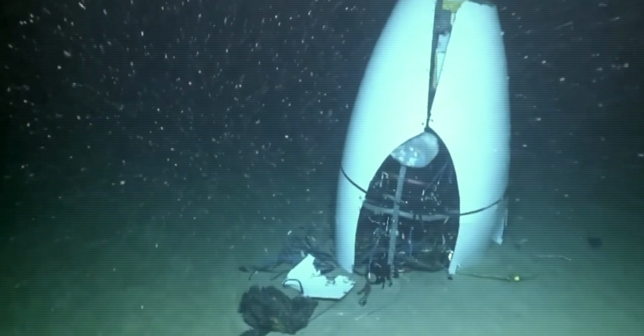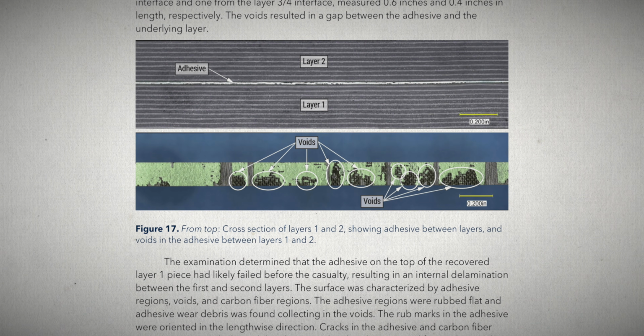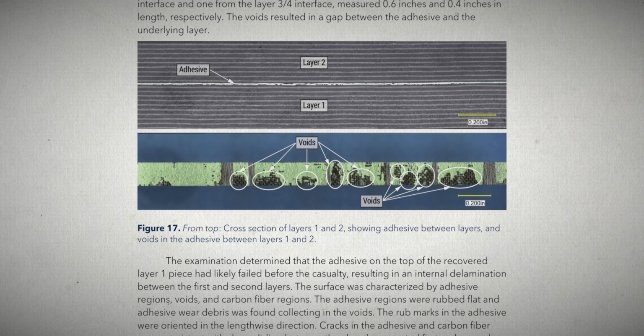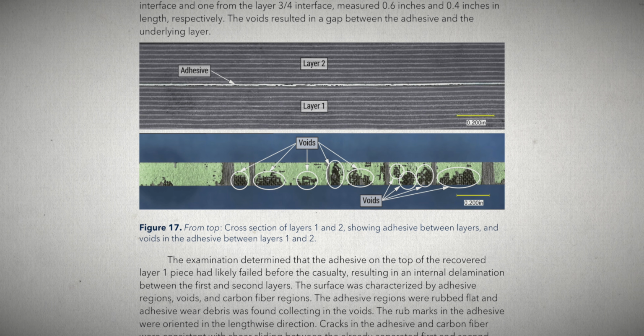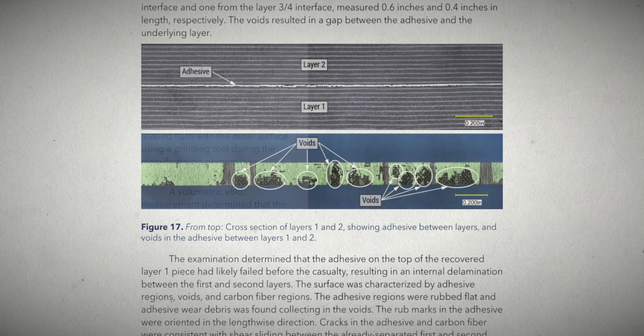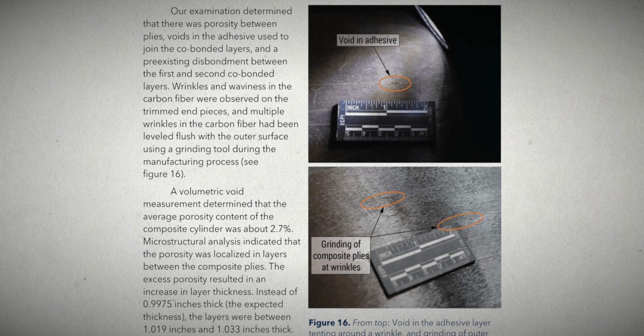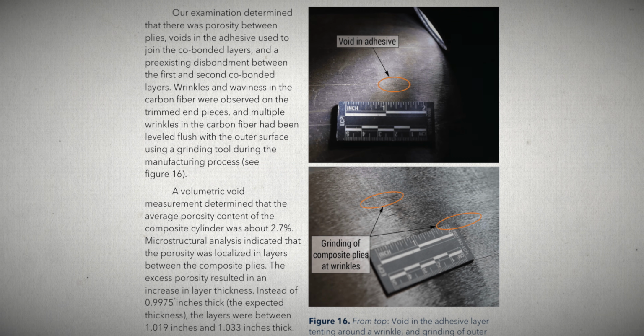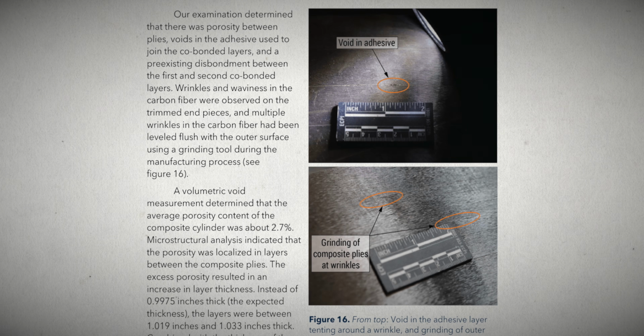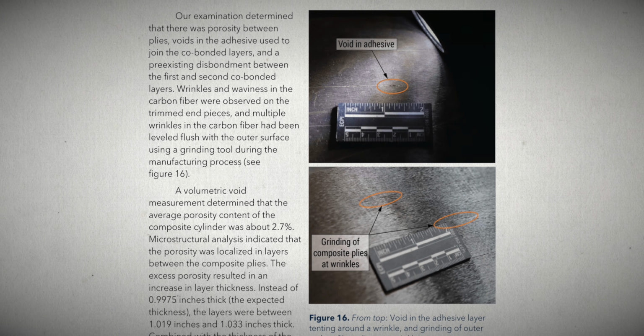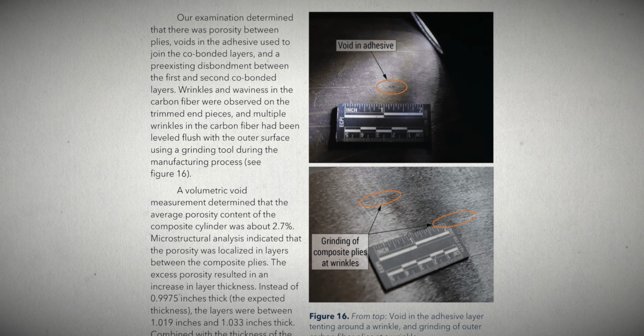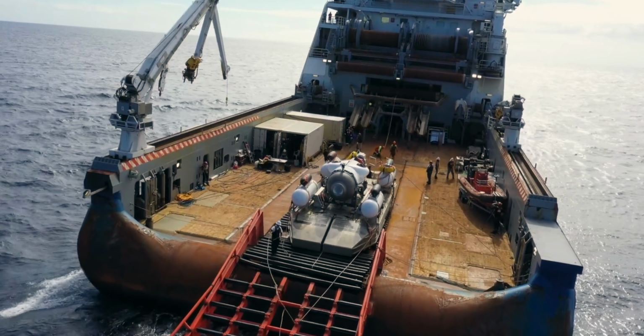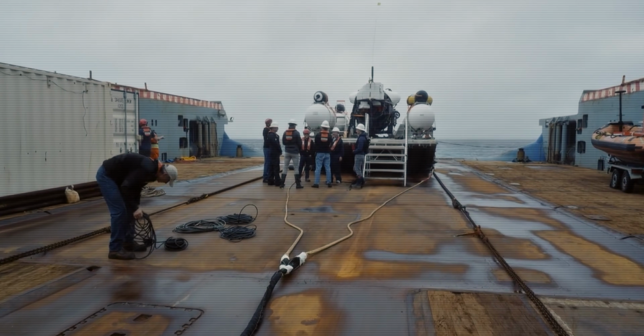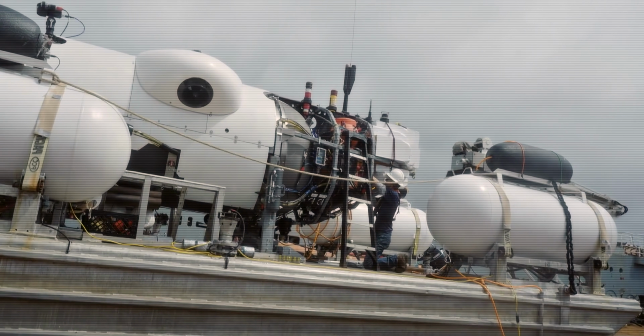The recovered wreckage told a different story. Investigators found extensive delamination between the first and second laminate sections, and again between the third and fourth, the same locations where manufacturing defects had been previously identified. Investigators also found wear marks and debris trapped between the separated layers, indicating that the laminate surfaces had been rubbing against one another before the final dive. These findings suggest that significant internal damage had already developed well before Titan's last descent.